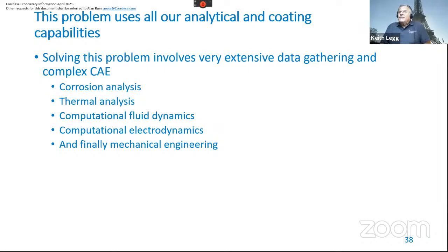And the answer is, well, if you're careful the way you do it, you don't get stress corrosion cracking. The fatigue is not bad because even though it's a hard coating, it's not like hard chrome, which is really bad for fatigue. But for zinc nickel, if it's hard, it means it will stand up to getting damaged much better. There are places where that's bad and places where that's good, but we're kind of stuck. We can't use cad anymore, so we have to use something, and we can't use zinc, which would be nice and soft too.